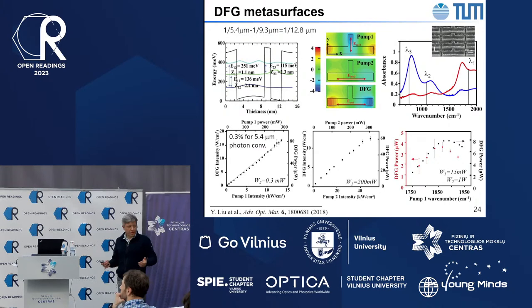So here we did the demonstration where we could generate difference frequency generation. We have two lasers, 5.4 and 9.3. And a similar type of quantum well design optimized for this difference frequency mixing. Antennas, again, similar concept, still T-shapes. We could not, despite trying several different shapes that were originally promising, T-shapes still give us the best results. So here, two resonances of these T-shaped antennas. This is for the input lambda 1. This is for another input lambda 2. And this is for the output lambda 3. They're not exactly well matched, because you always have some fabrication errors, but they're well enough matched.